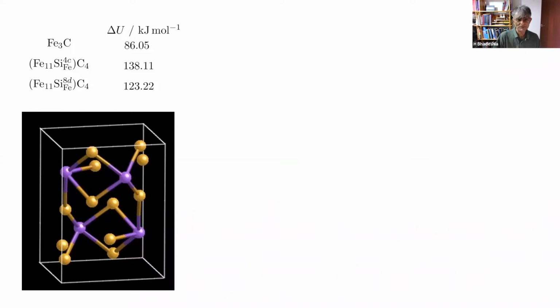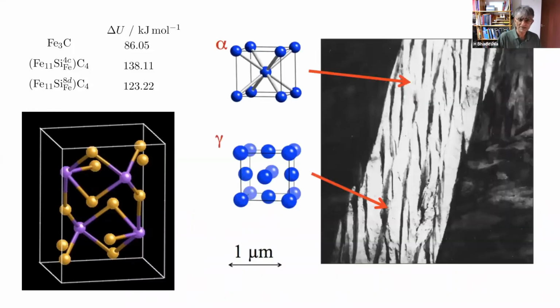Okay, so when we do that, we have a handle on how much silicon to add, and you end up with a beautiful structure here with plates of ferrite which are only 1/4 of a micrometer in thickness, separated by these carbon-enriched films of austenite, produced extremely cheaply simply by partitioning carbon. Okay, there's no nickel, nothing necessary there. And it should form a perfect composite because austenite does not have a ductile brittle transition temperature and ferrite is strong.